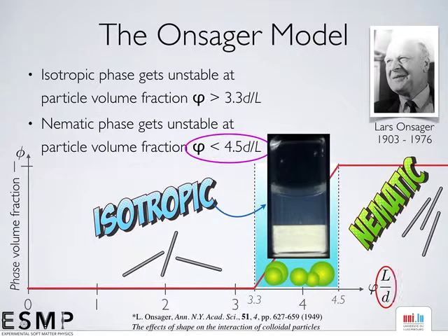And the reason that this is interesting is that the threshold for liquid crystal formation is proportional to L over D, the aspect ratio. So if you have a polydisperse system, if you have a local fluctuation in aspect ratio, then a certain volume with larger aspect ratio will first form the liquid crystal phase. So these liquid crystal forming tactoids will have a larger aspect ratio. And the others will have a lower aspect ratio.